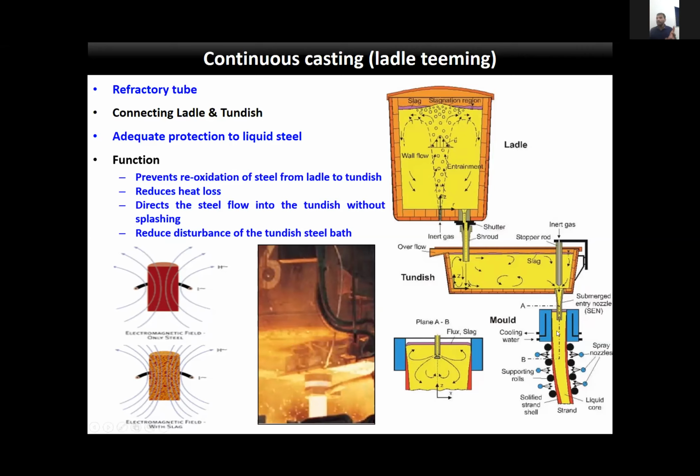The slags are nothing but non-metallic particles, or you can say these are detrimental foreign entities, which will deteriorate the steel properties. So you have to avoid this vortex formation. There are some techniques, through electromagnetic fields or sensors, used to detect when the slag is passing through the ladle, and then they will stop the teeming process and throw out the leftover metal and the slag. That will also affect yield. If your vortex forms at considerably higher heights, then you may lose most of your steel value.